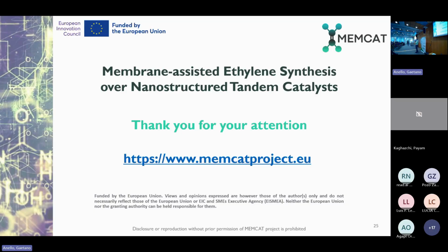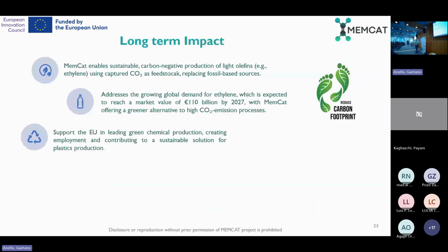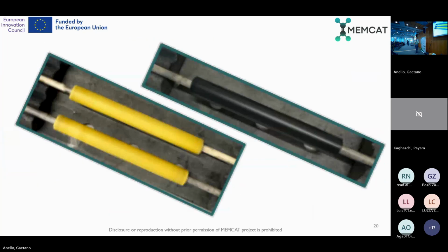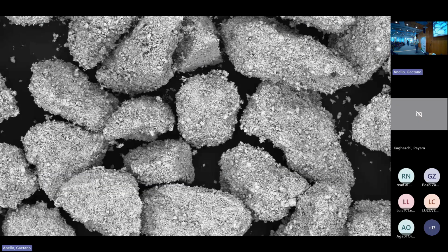And this photo I was showing, this is quite large scale. It's actually a pressed and sieved fraction between 200 and 350 micrometers. But the metal catalyst is around 10 nanometers. Then you heat them up to 300 degrees. Yes, we go up to 400, but our target is also to try to reduce temperatures as much as